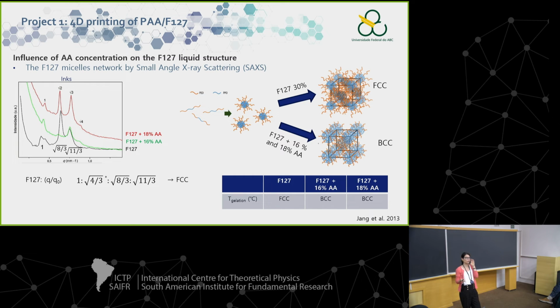So in the case of Pluronic, we end up with an FCC structure. And when we mix it with acrylic acid, we end up with a BCC structure. So there is an influence of acrylic acid on the liquid crystal that is formed. And now we are trying to understand and explain why, possibly due to hydrogen bonding between the different parts of this copolymer.